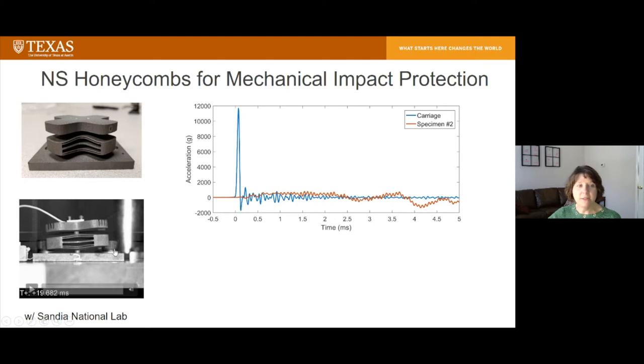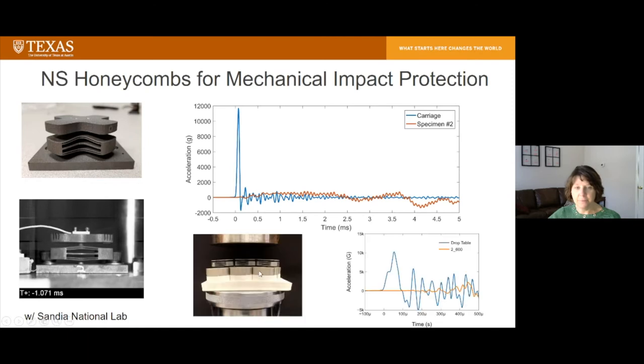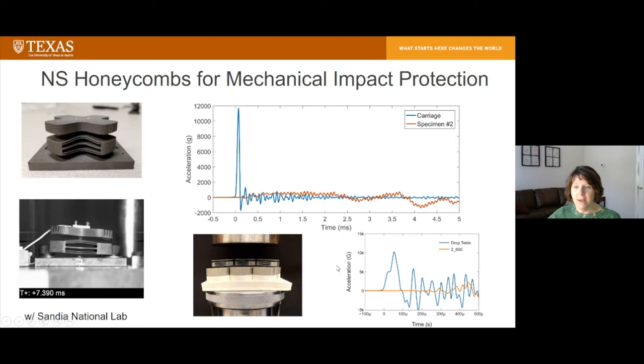And then in red, you can see what you would feel if you were riding on top of our element as opposed to just on the carriage. And you can see, again, an order of magnitude reduction in acceleration. We can also apply these somewhat conformally. Here you can see them sort of wrapping around a base and similarly applying an impact load and cutting it down again by an order of magnitude.